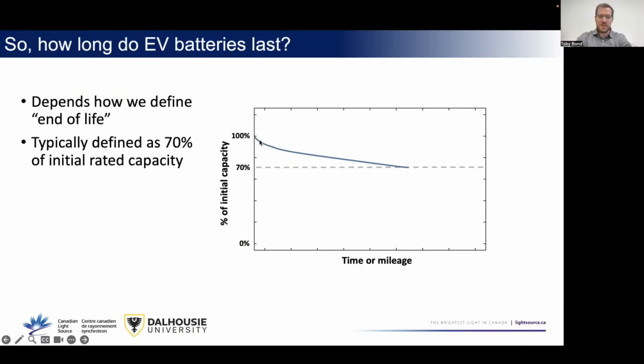When you have this degradation of capacity, the amount of charge that the battery can store over time, we call this capacity fade. It typically has this kind of shape to it, where you have an initial steeper loss of capacity, and then it plateaus out and is slower. This comes from that effect I was talking about before, where you have that initial fast reaction of that surface film, and then that surface film makes the further reactions slower and slower. So after that point, it might keep going very linearly, very regularly.